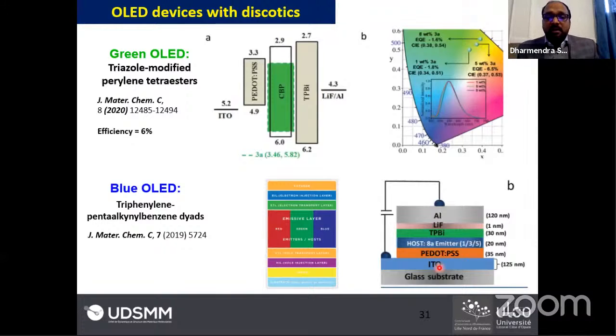So why are we talking about the photonic applications of discotic liquid crystals? Because they are fluorescent in nature. So based on these triazole-modified perylene tetraester and triphenylene-pentaalkynylbenzene dyads, we fabricated some OLED applications with the help of our Taiwan collaborators. And it is shown that the perylene-based compound shows a green OLED application with an efficiency of 6%. So it's really a very great achievement.